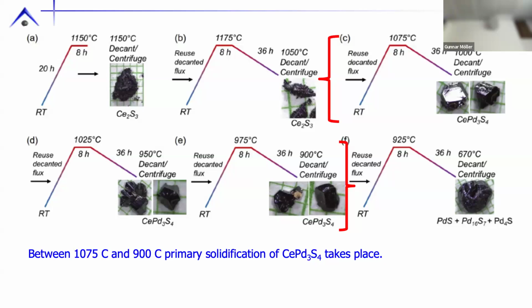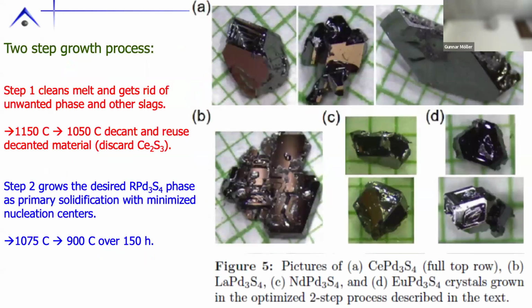Okay, I can heat up, I can cool down, and repeat the next morning. So in a week's time, we can go through steps like this and identify the region we're interested in. And once we've identified it, we can then do much slower coolings. So now that I've identified the right region, I get rid of nucleation sites and I slow cool over the magic region. And I've gone from things that are tiny submillimeters to things that are almost getting into centimeter sized, which is lovely. Did I answer your question?